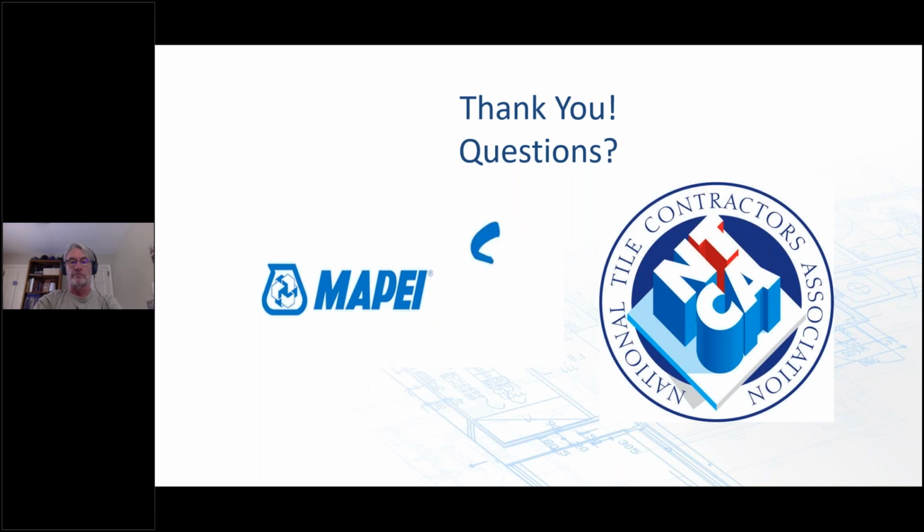But for tile, again, you've got a minimum of 3,000 psi compressive strength for the standard, and then it's really more of a question of drying time. They differentiate by whether you can install the next day or within a few hours. That's really the big differentiating factor here, and then you can also compare the prep requirements. Does it need a CSP? Does it not need a CSP of 2 to 3? Different products have different requirements.